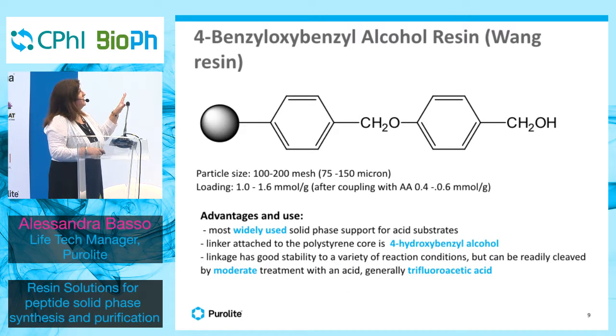This resin is already a pre-linked resin, a very old style resin, widely used in solid phase synthesis for acid substrates, so it's good for the Fmoc chemistry. The linker is attached to the polystyrene through the hydroxybenzyl alcohol, and the cleavage is done with trifluoroacetic acid.